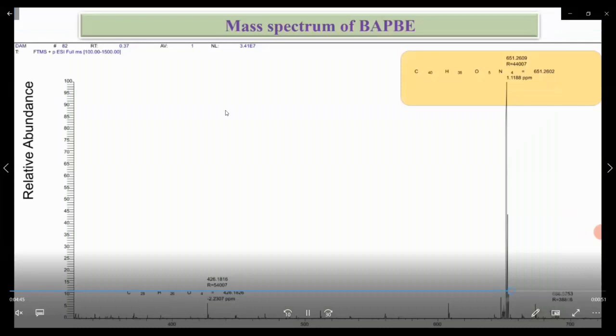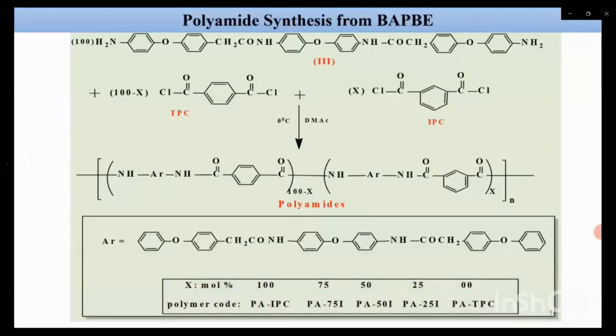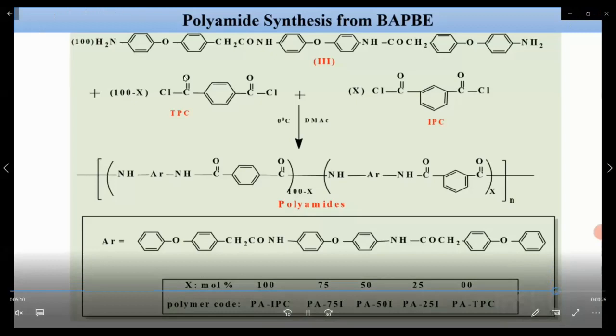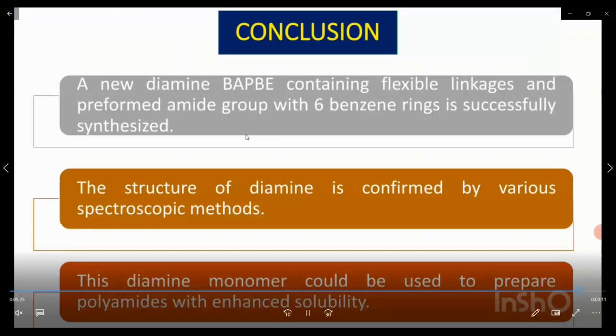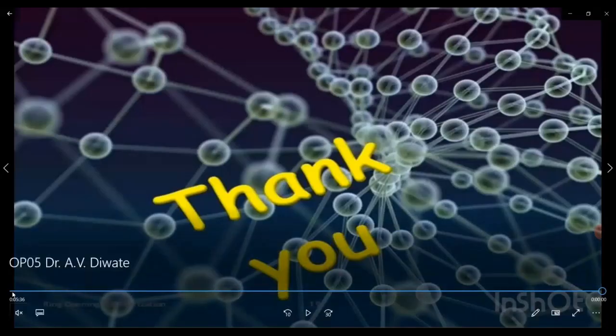The mass spectrum of this diamine shows an m/z ratio at 651, which shows the molecular weight of this monomer, C40H35O5N4, which is the M plus 1 ion peak. This monomer can be utilized to produce this type of polymer containing flexible ether and methylene linkages, which improves the solubility and processability of the polymer. In conclusion, a new diamine containing flexible linkages and preformed amide groups with six benzene rings is successfully synthesized.